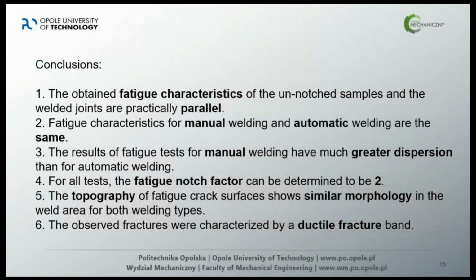And in the end, some conclusions. The obtained fatigue characteristics of unnotched samples and the welded joints are practically parallel. Fatigue characteristics for manual welding and automatic welding are the same. The results of fatigue tests for manual welding have much greater dispersion than for automatic welding. It is very important. For all tests, the fatigue notch factor can be determined to be 2. The topography of the fatigue crack surface shows similar morphology in the weld area for both welding types. The observed fractures were characterized by a ductile fracture. Thank you for your attention.